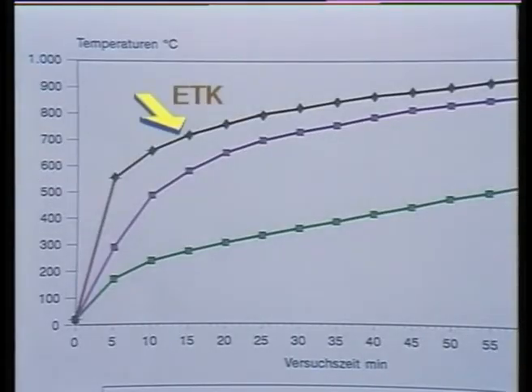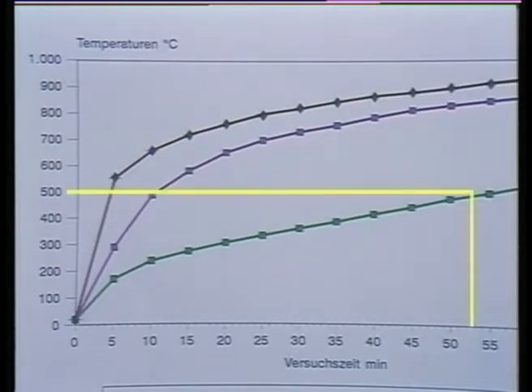The temperature graph shows 3 temperature curves: the standard temperature curve, top, the temperature curve for the untreated steel, middle, and the temperature curve for the temperature readings taken on the rear surface of the steel plate coated with Hensotherm 3KS HF, bottom. In small fire testing of coated steel plates, a temperature of 500 degrees Celsius in the center of the plate on the side not facing the fire must not be reached until the time specified as the basis for award of the permit has elapsed.